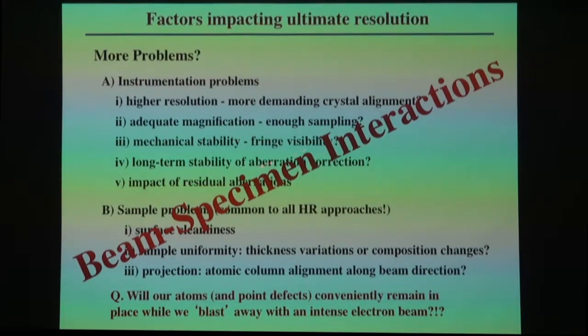And overarching across all of these things to take into account, the possibility, the likelihood, the almost inevitable beam specimen interactions. We rely on the interactions between the beam and our sample for inelastic scattering to get all the EELS and other types of information, elastic scattering to get the high resolution images. You have to ask yourself the question always, will the atoms and the point defects, if that's what you're looking for, will they stay in place while you blast away with your intense electron beam? It's an incredibly intense beam when you start doing these aberration corrected probes, and you sit the probe in one little position on a little square angstrom of your sample for very long. You're going to drill a hole through most self-respecting samples very quickly. And so you have to go back and check. Has my sample changed during the observation period?